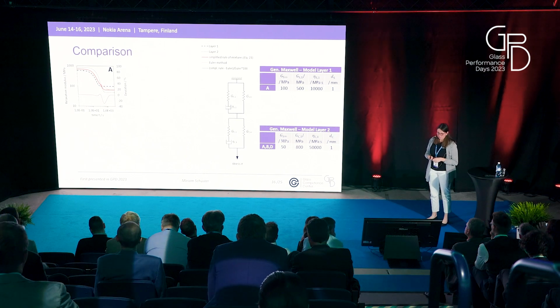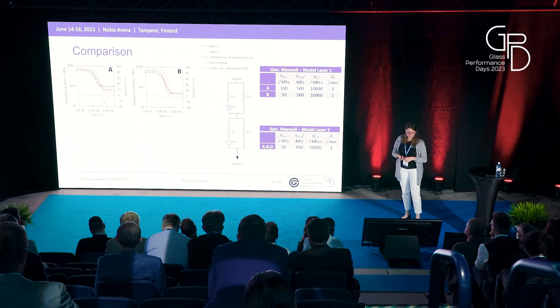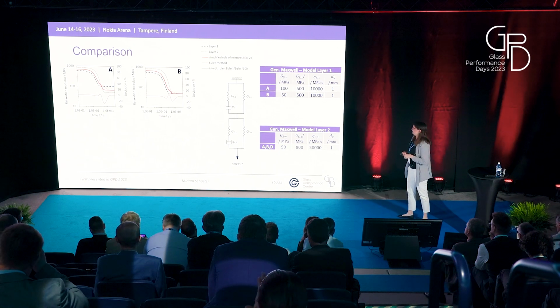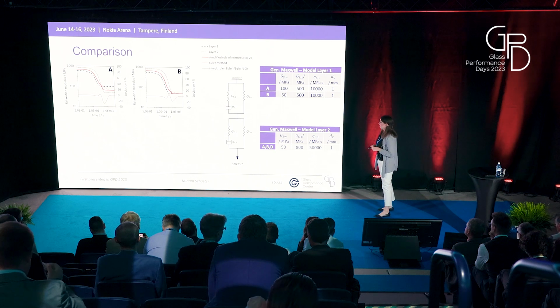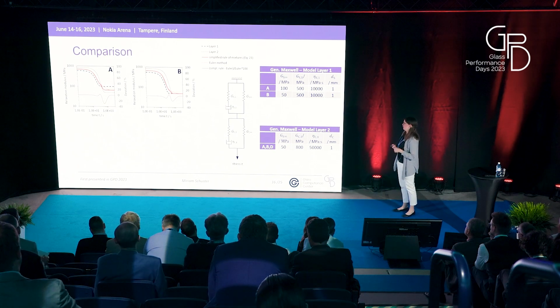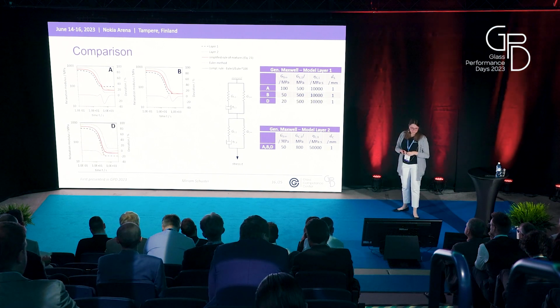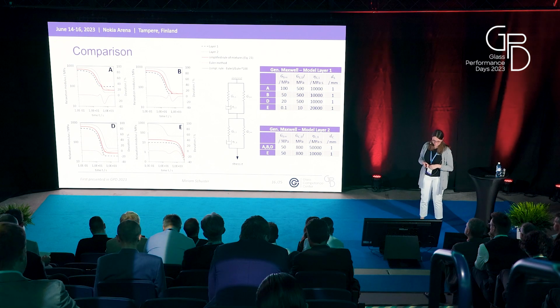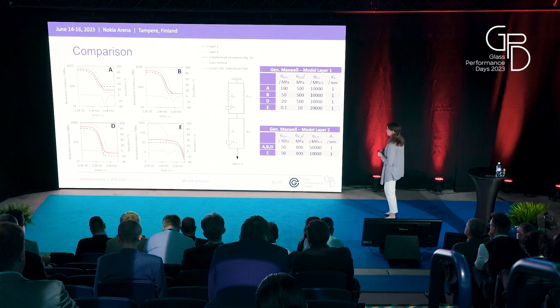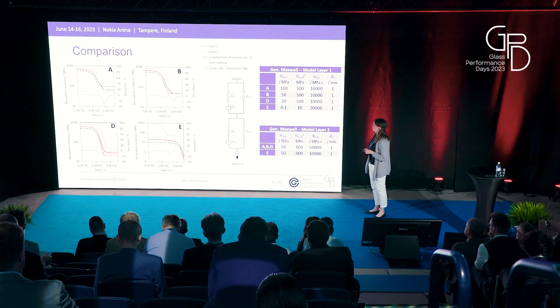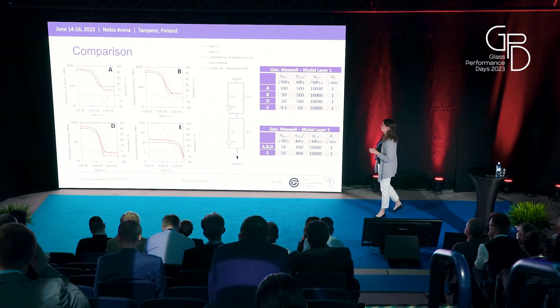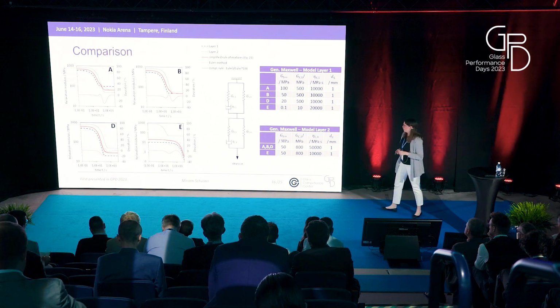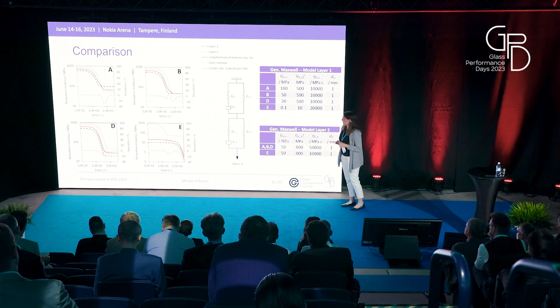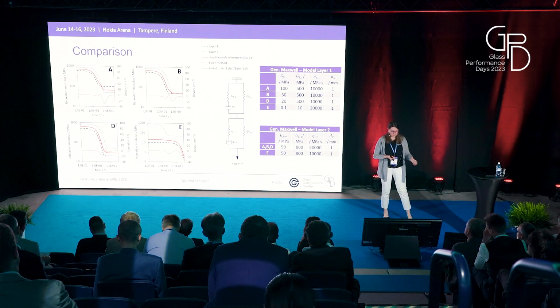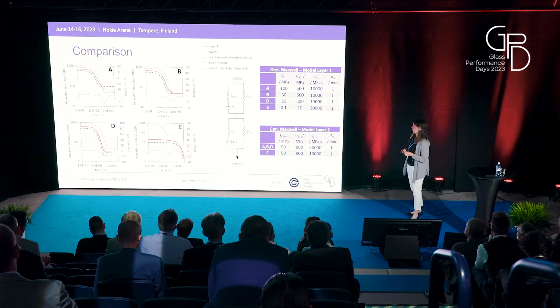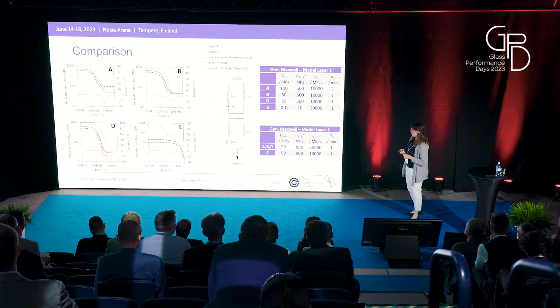And here I've also varied the parameters. For example, in this example B, we have another combination of material parameters. And here again, we see that there is a deviation between the exact and the simplified solution. But when we are looking at, again, other combinations, for example, for D and E, we see that the deviation between the exact and simplified solution becomes a bit smaller. We do also see in the example E that when one of both layers is very soft, then the multilayer will also behave soft. So the influence of the softer layer is very high.